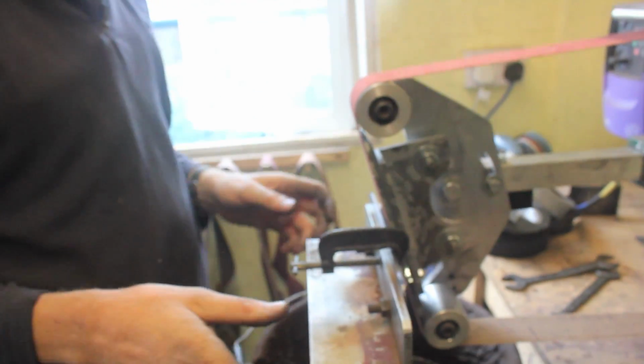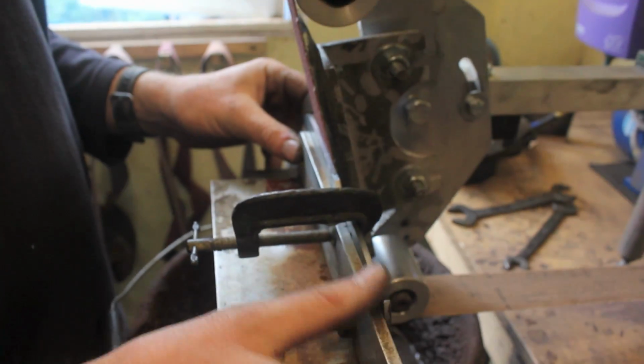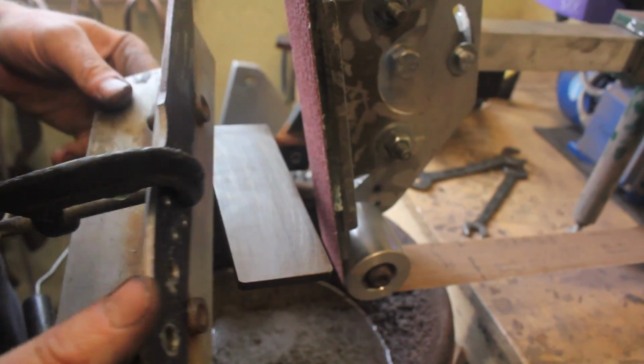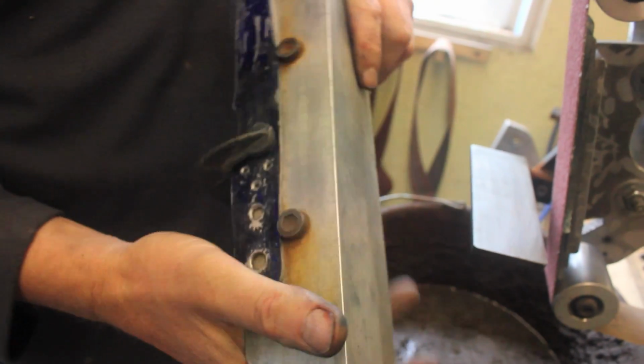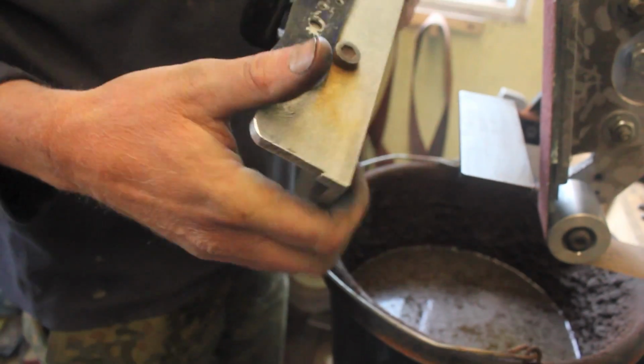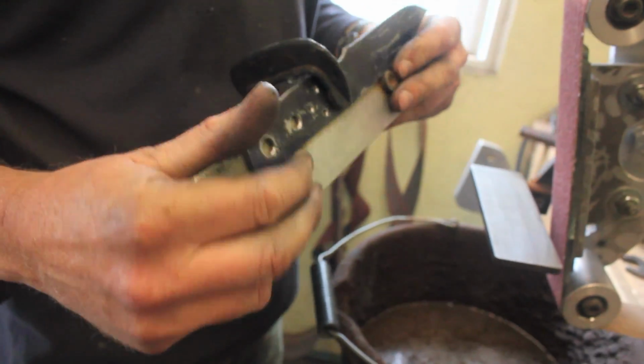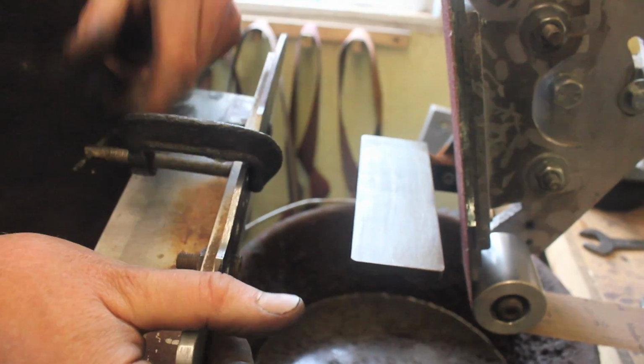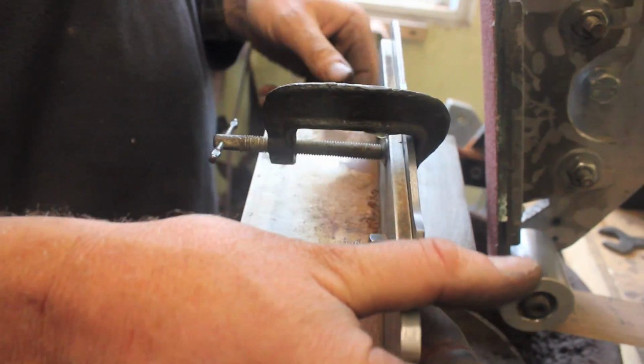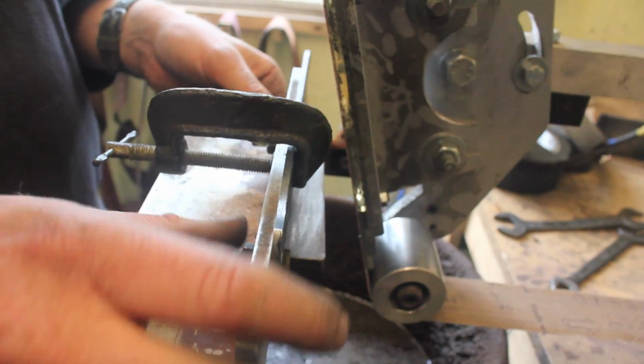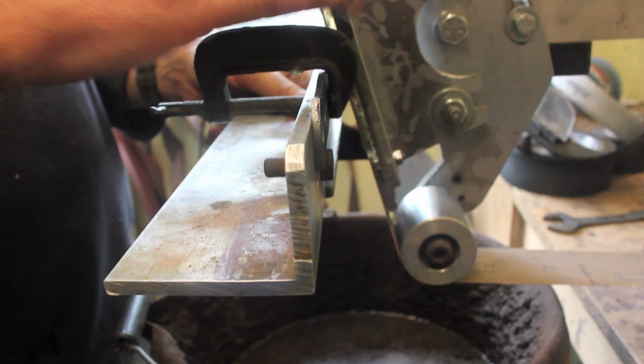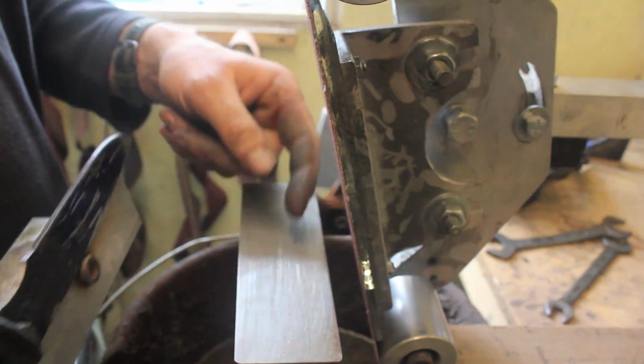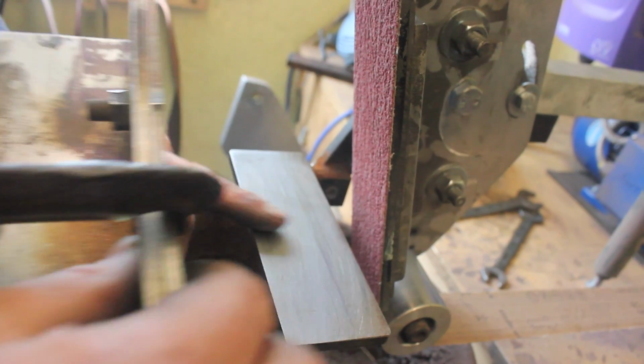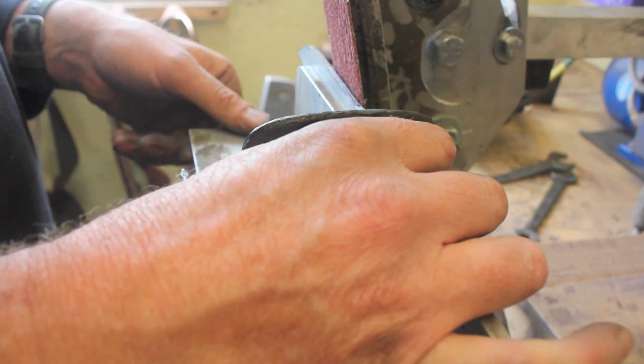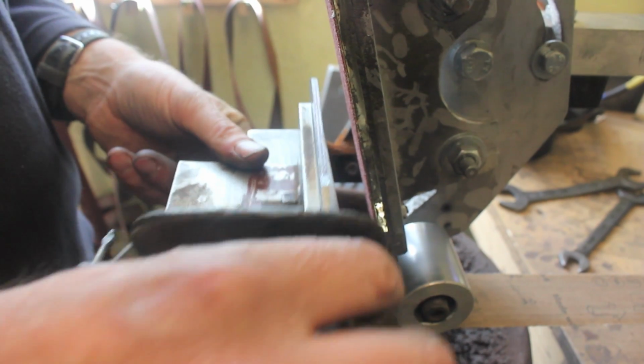Okay. Well, for consistency, I have learnt to grind freehand, but for consistency and speed I will use a jig, and basically this is just a piece of angle iron or angled aluminium, I think, and a couple of studs to rest the knife on at the correct angle, and I've used a G-cramp to keep it onto the jig. And it's just a matter now of I set the angle up on the platen. This is called the platen. This is a tool rest, so the angle there set up to what I want. It's just a matter now of just grinding that off down to those lines.